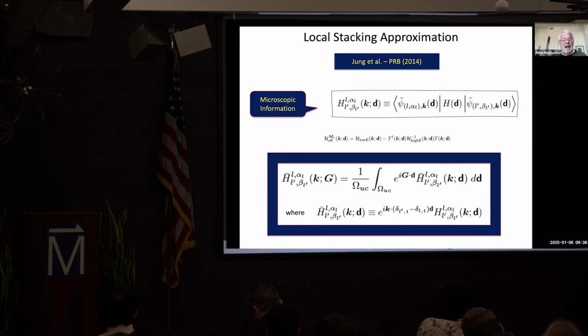And typically, within a shell of momentum, all of the parameters are related to each other by symmetry. So that leaves you with a Hamiltonian that depends only on a small number of parameters. Those parameters are basically these Fourier transforms with respect to displacement. It's just a way of simply characterizing the dependence of the local Hamiltonian on stacking. And so there's two little asterisks I need to apply here.